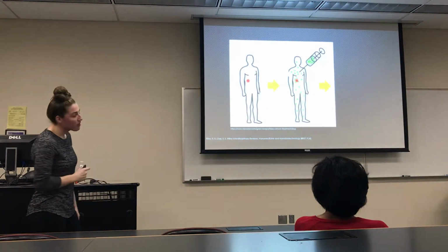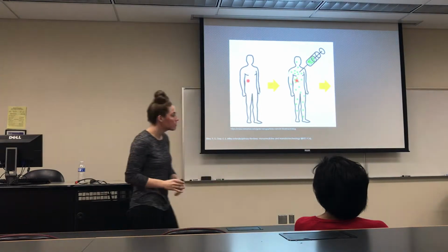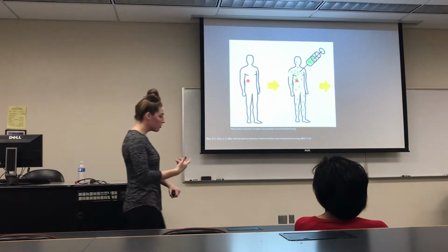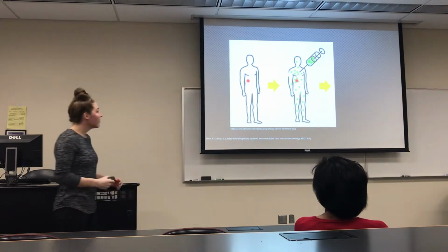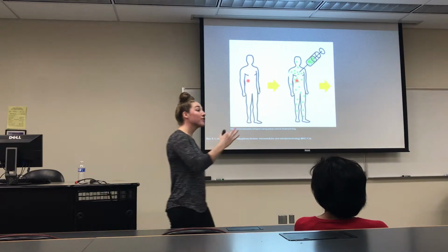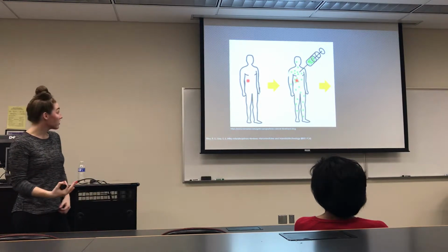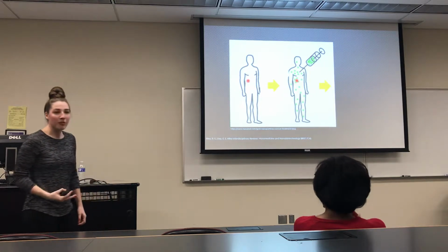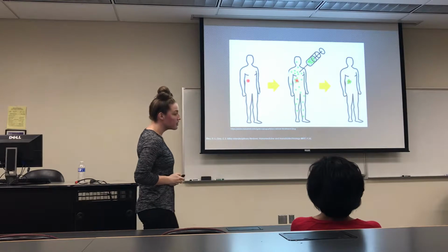However, there is a slight issue with the way that we actually introduce the nanoparticles into the tumor tissues. The human body is primarily made of water. So when we introduce the nanoparticles into the tissue, we dilute them. Instead of having that concentration of aggregates, the nanoparticles can spread out, and then we don't get as many nanoparticles getting into those tumor cells as we would like. That means not enough energy is formed to get enough increase in temperature to kill off those tumor cells. So what we want to do is find a way to promote aggregation.